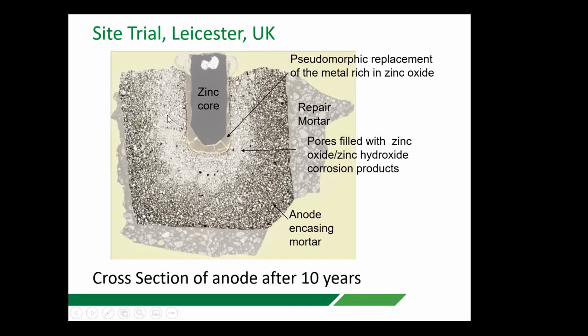But we also noticed that the zinc oxide was able to migrate into the pore structure of the cementitious material, quite a long distance, particularly on this side where you had more of the corrosion, quite a distance into the encasing mortar. And that was what was actually being hoped for, because we know that zinc in a very high alkali environment, when it corrodes, the corrosion products remain soluble. They're zincate ions, and they're able to migrate within the pore structure. They then obviously, when supersaturation is exceeded, precipitate out as zinc oxide. But we can see that we are able to move the corrosion product quite a distance away. That means that you're not really concentrating them too much at the interface, and you're still allowing the electrolyte to be in contact with the zinc, and the corrosion of the zinc will continue to occur.